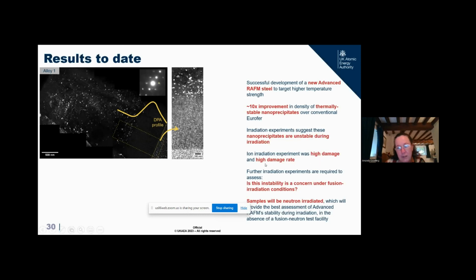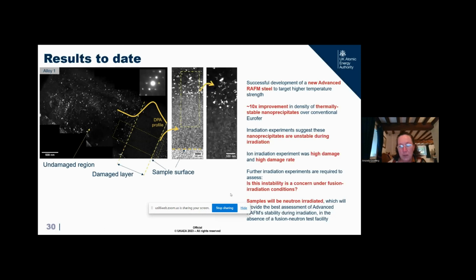And if we did the damage imposition at a slower rate and to a more incremental degree, and allowed for some of that annealing I spoke about earlier and that self-healing, would we still see the situation that we see at the moment? So this is a very first result, and it comes from an ion irradiation and not a neutron irradiation. So what we want to make sure going forward is that we iterate this work and we see if we get something a little better.